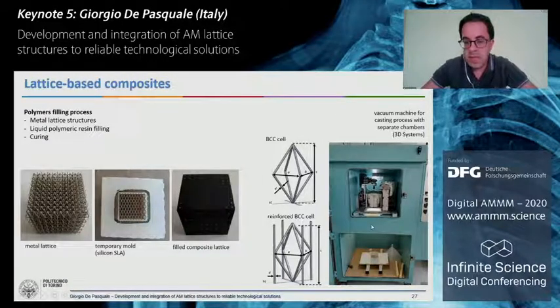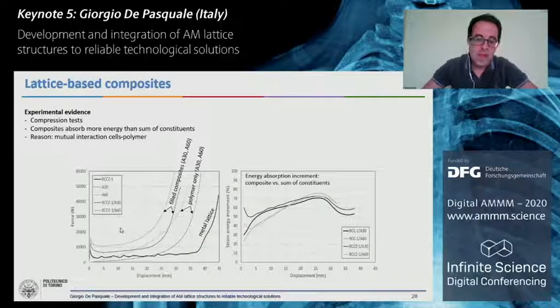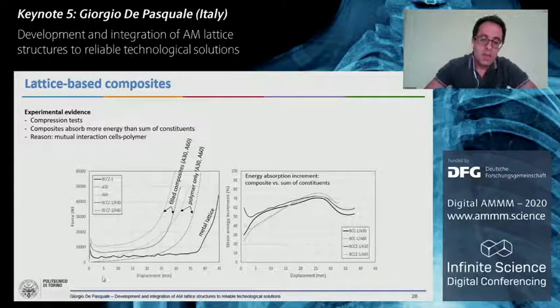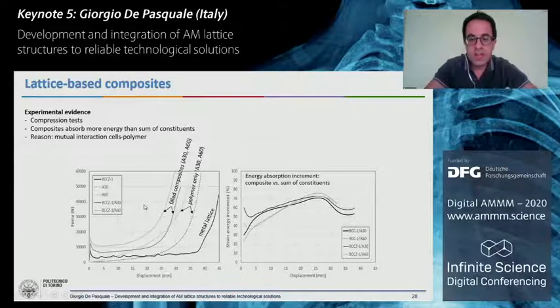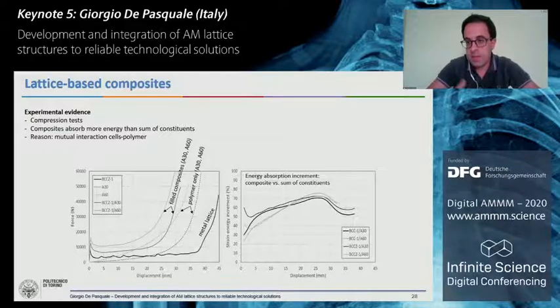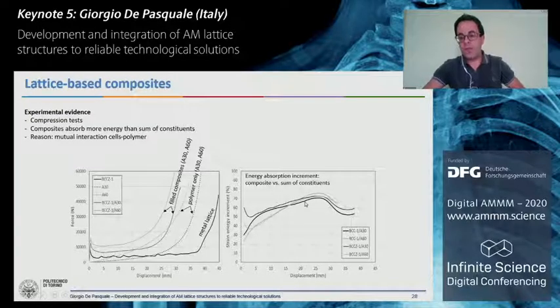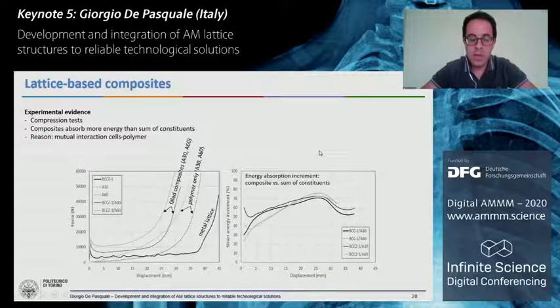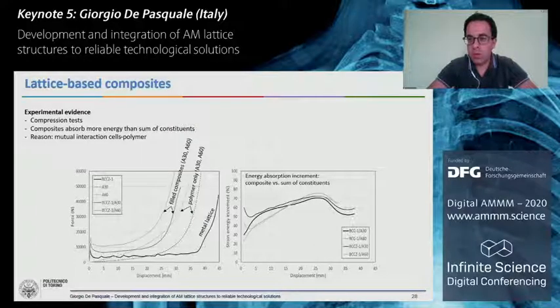A specific equipment is needed to do this, but the very interesting thing is what is reported here on the left, where we have the force displacement curve of the pure lattice, the black line, only lattice, then only polymer, the dashed lines. We have two dashed lines because we tested two polymers with two different hardness. And the gray lines are instead the composite material. So the result is that the elastoplastic energy absorbed by the composite is higher than the sum of the two energies absorbed by each of the two components. And this increase of energy absorption, as we can see on the right, can reach also 70%. So it's a pretty high increment of energy absorption that makes this composite very suitable for impact absorption applications.